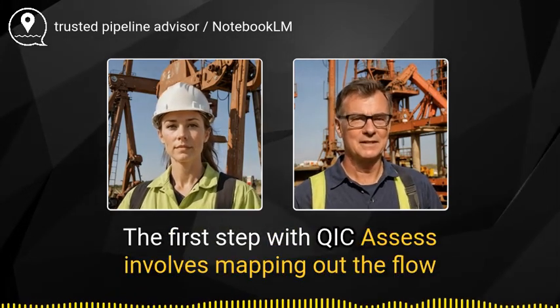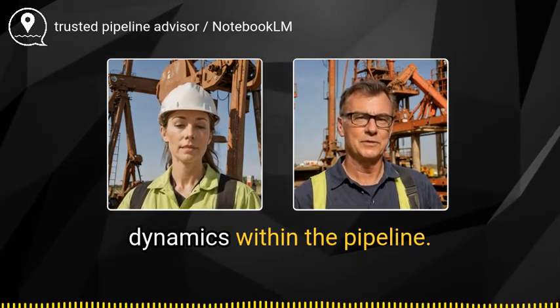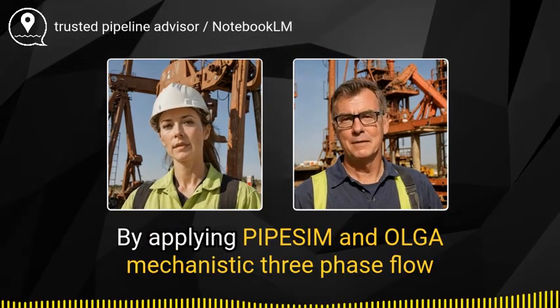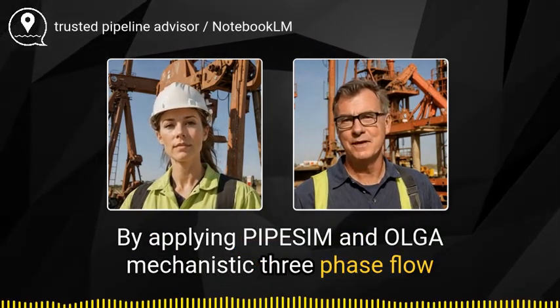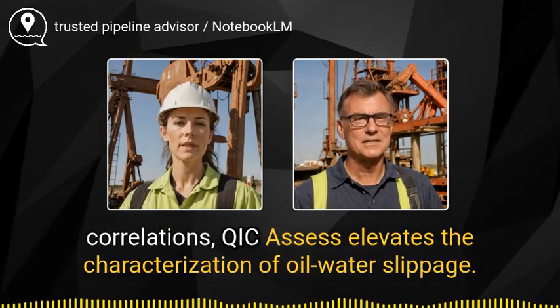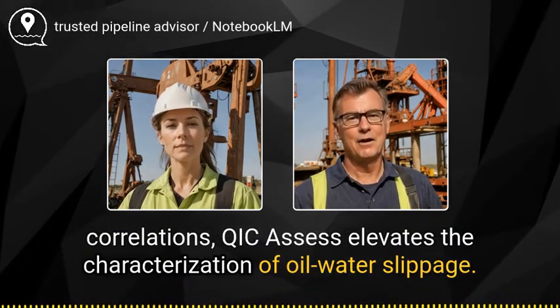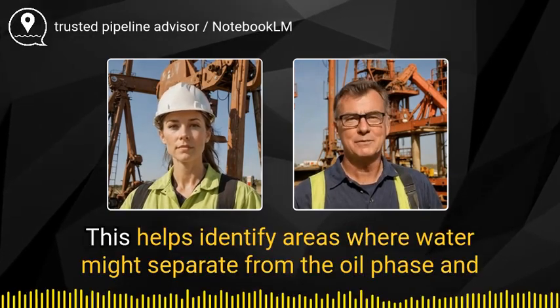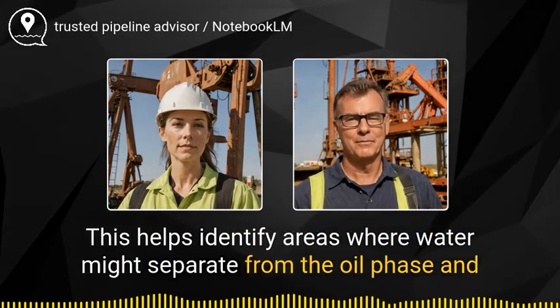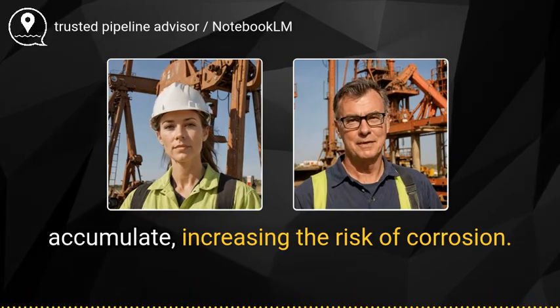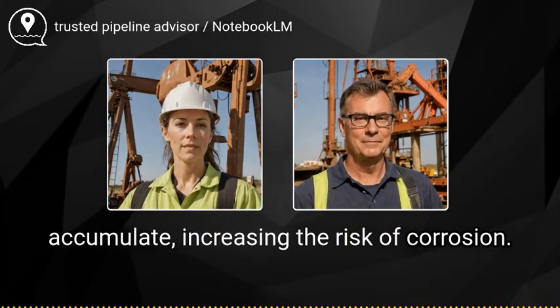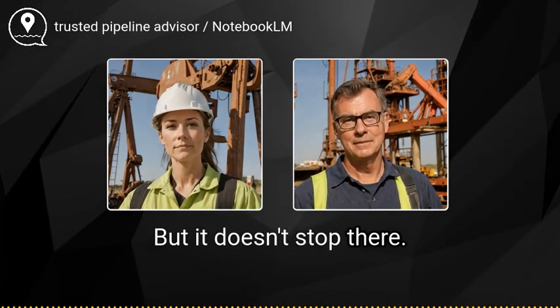The first step with QIC Assess involves mapping out the flow dynamics within the pipeline. By applying PIPESIM and OLGA mechanistic three-phase flow correlations, QIC Assess elevates the characterization of oil-water slippage. This helps identify areas where water might separate from the oil phase and accumulate, increasing the risk of corrosion. But it doesn't stop there.